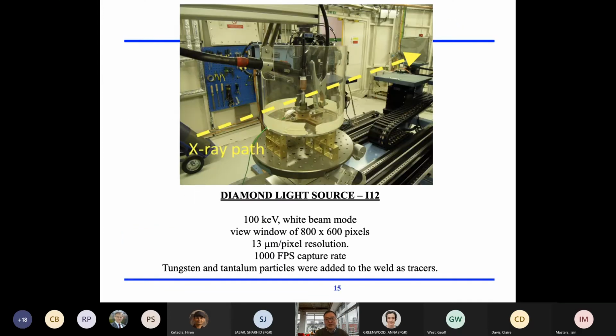So this is what it looks like. This is our sample sitting in there, and the X-ray passes over there, and this is the surrounding area to make sure the liquid will not be splashed out. We tried 100 keV, as I showed earlier. We want to see probably as many photons as possible. We use a white beam mode, and at that time we got about 13 micrometer pixel resolution, and we can get 1,000 frames per second as captured. We also tried 2,000 frames per second.